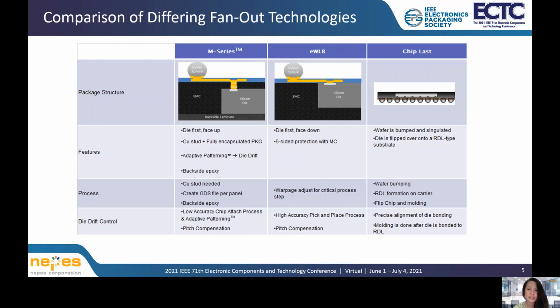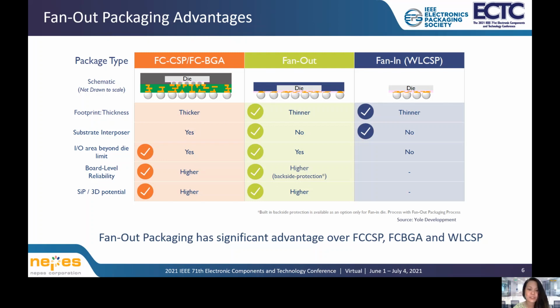For EWLB, back-end processing such as back grind and singulation will need to be completed before reconstitution process. Die will be placed face down onto the temporary carrier. One key item to note for EWLB is that mold compound material is not protecting the active side of the die. In comparison to flip chip CSP, flip chip BGA, and wafer level CSP, the fan-out structure provides scalability to significantly increase routing density, while the thin film process provides a reduction in package size and thickness as opposed to substrate-based packages. Fan-out in comparison to wafer level CSP has higher board reliability, lower thermal, and the potential for integration of multiple dies, 3D package on package, and system in package.